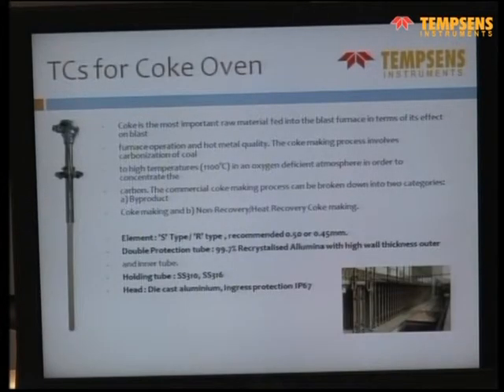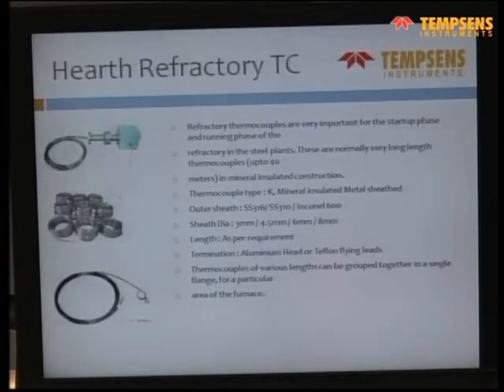For the coke oven, it is again a similar kind of thing, but with a double ceramic tube, and it is used for coke oven battery application. So this is long length, can be up to 2 meter long thermocouples for such cases. Then these are for the refractory thermocouples. For a steel plant refractory, the first one, as you see in the box, is a multi-point thermocouple. There are different positions in the refractory. Sensors are laid inside the refractory and it gives the temperature at different points and different levels in one box. The second is also the refractory thermocouples for different lengths.